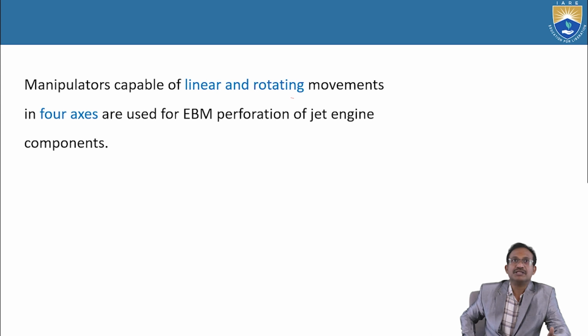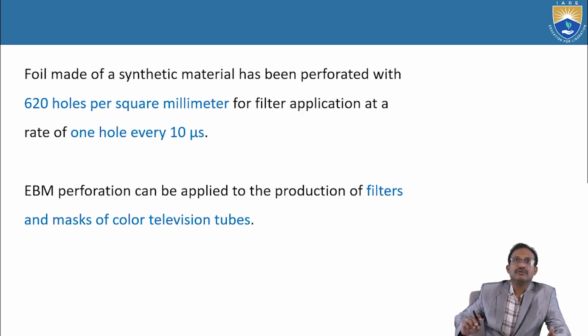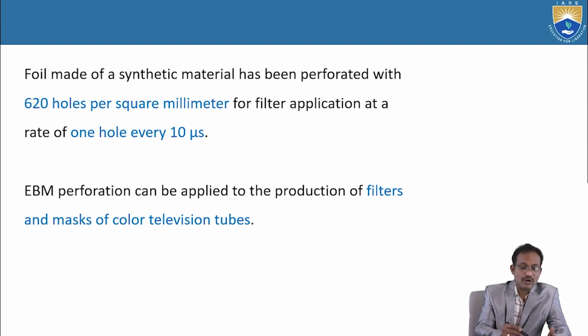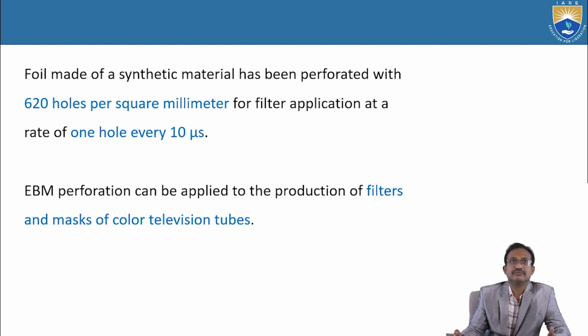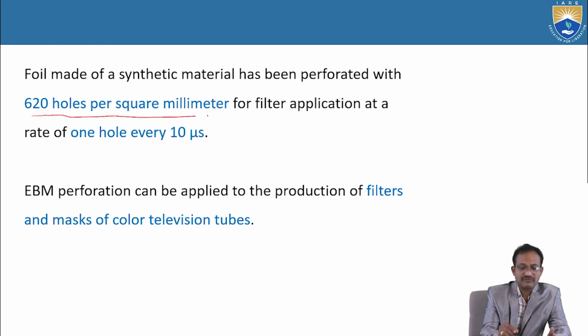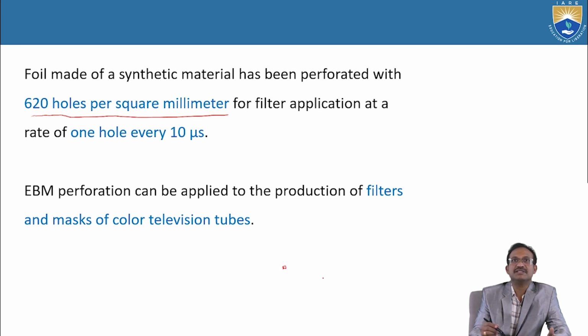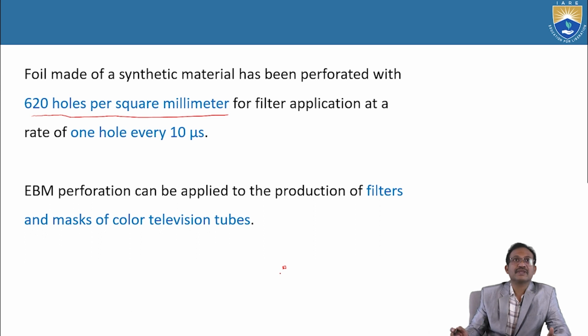This is an important application for perforation of sheets. Foil made of a synthetic material has been perforated with 620 holes per square millimeter for filter application at a rate of 1 hole every 10 microseconds. Sorry, square millimeter. One square millimeter means almost just a dot. Within that, 620 holes. Can you imagine?